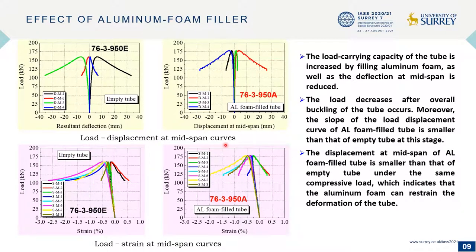The load versus displacement at mid-span curves and the load versus strain at mid-span curves for both empty tubes and aluminum foam-filled tubes are plotted. The load carrying capacity of the tube is increased by filling aluminum foam, and the deflection at mid-span is reduced.